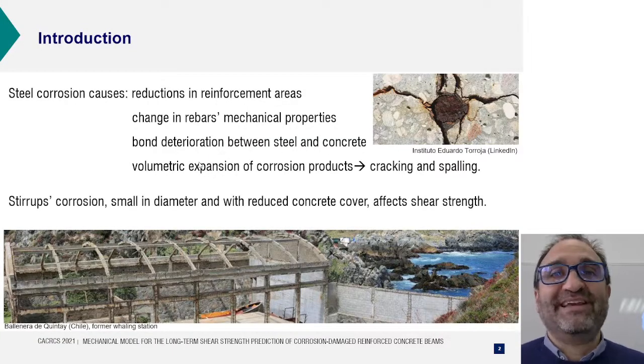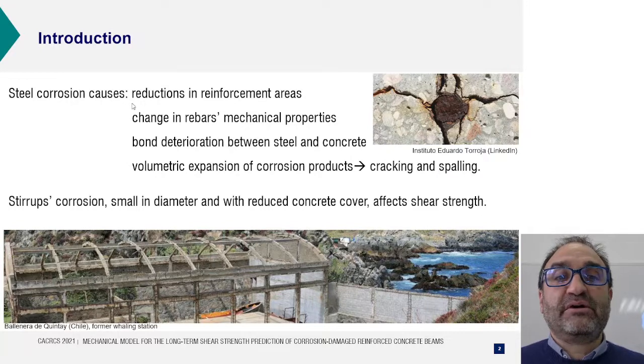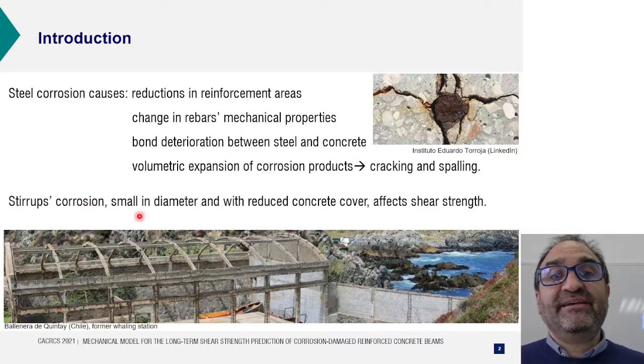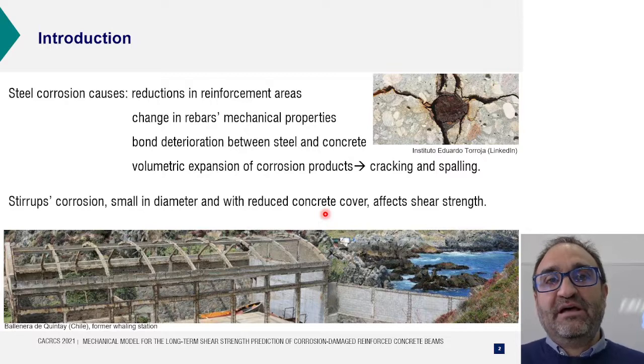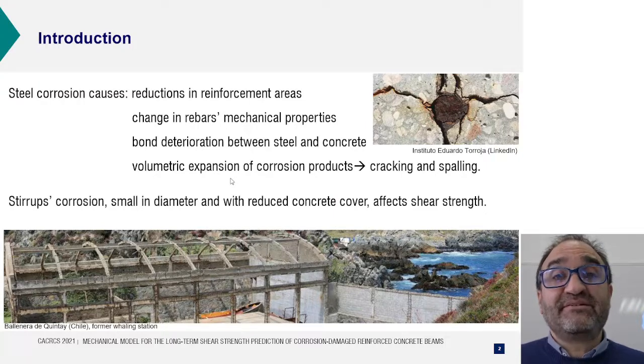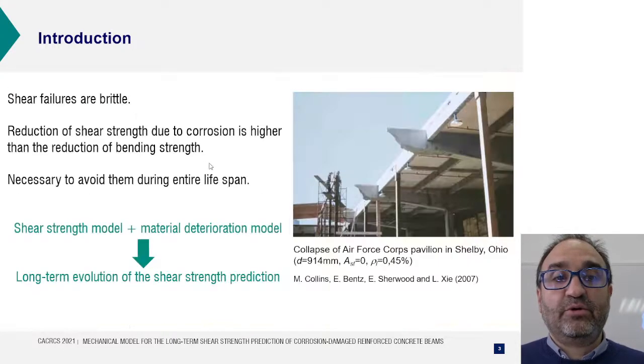It is well known, especially in this conference, that steel corrosion causes reduction in reinforcement areas, change in rebar's mechanical properties, bond deterioration between steel and concrete, and, due to the volumetric expansion of corrosion products, cracking, as you can see in this nice picture, and spalling. Moreover, stirrups are generally smaller in diameter than longitudinal reinforcement, and they present a reduced concrete cover with respect to the longitudinal reinforcement, so the shear strength is quickly affected by corrosion.